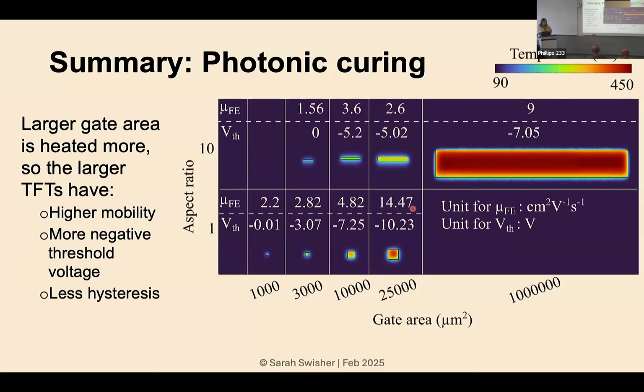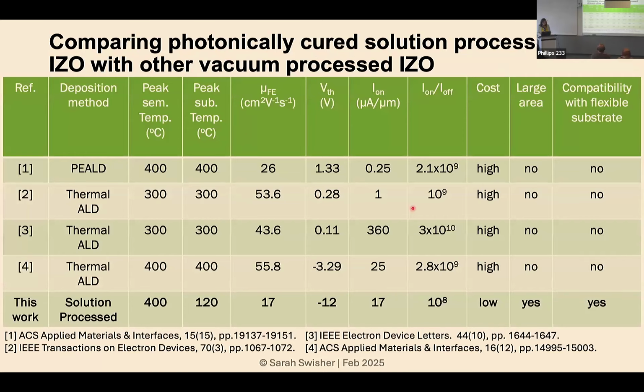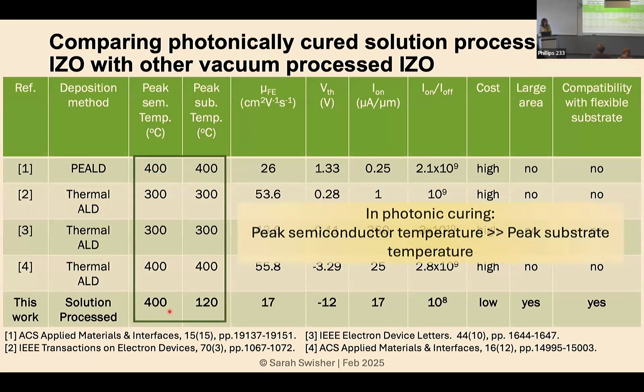And in this study, we're not trying to optimize the device performance, but we do want to know how this compares. And as I mentioned, this is a solution process method, but in the end, it's a thin film oxide, right? So we were curious to see how this compares to ALD films in particular. So these are several different ALD oxide films. Some are thermal, some are PEALD, and then our solution processed work is down here. One of the key things to note here is that we're highlighting the semiconductor curing temperature, and this is the substrate temperature.